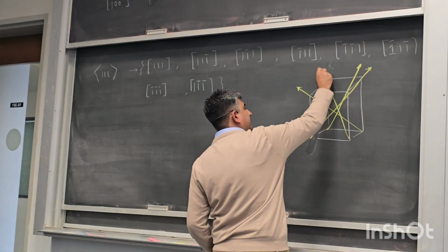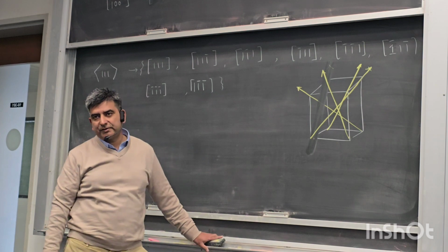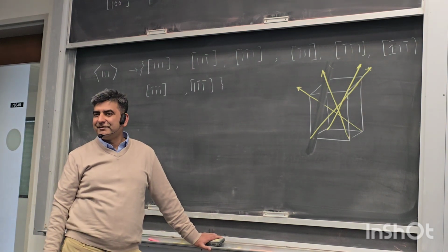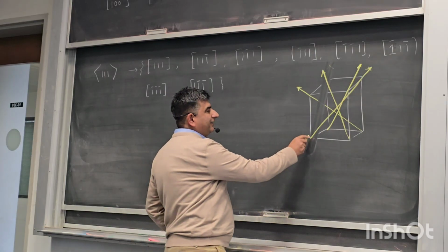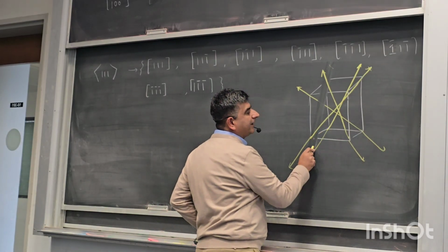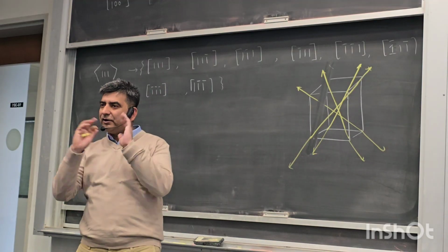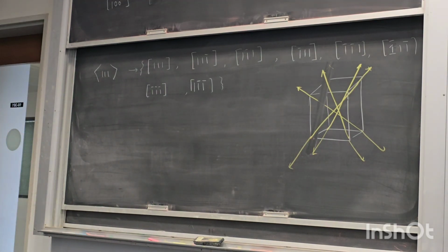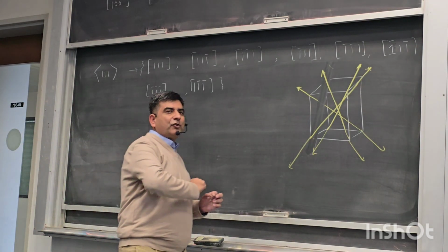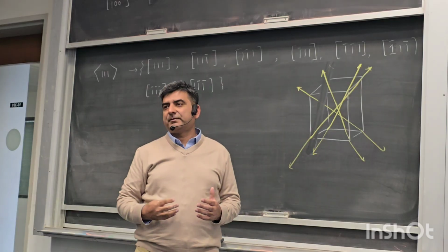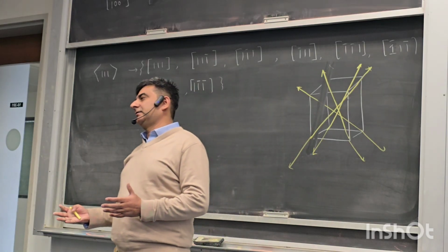And fourth. These are four directions corresponding to the four body diagonals. So you take these four directions and then you take the opposites to these. So you get 8 directions in total. All 8 of these directions are just the same. If there are atoms inside this crystal structure, then walking along any one of these directions, you get the same distribution of atoms, with the same spacing.